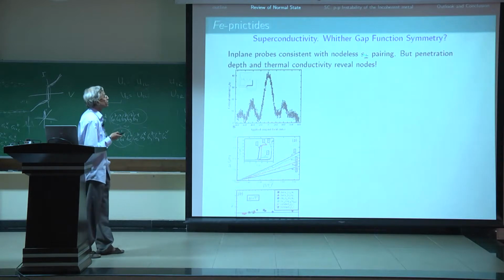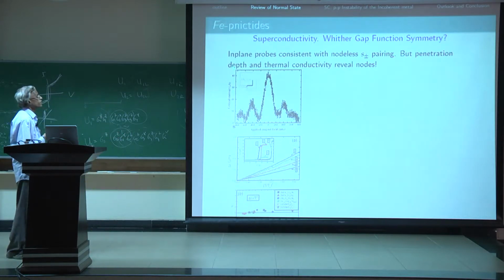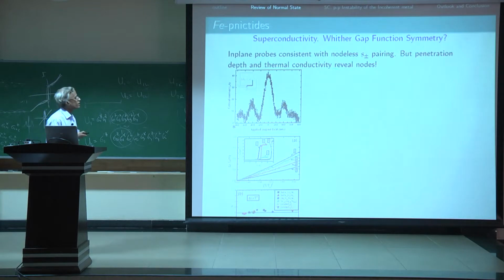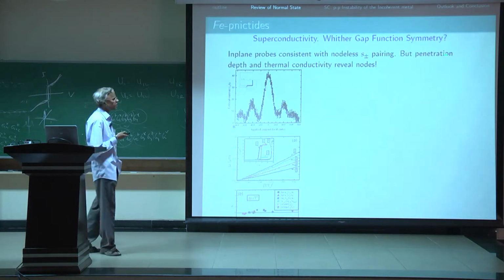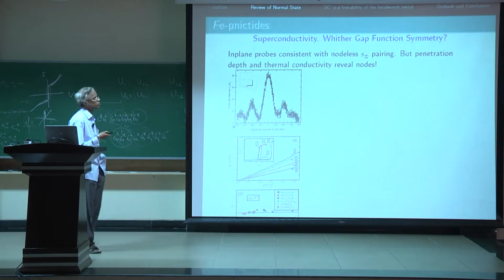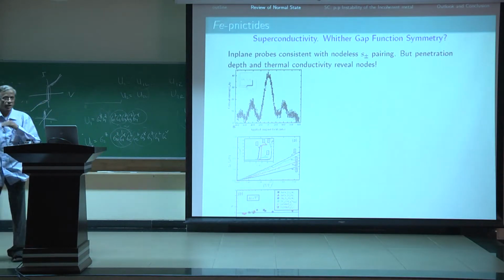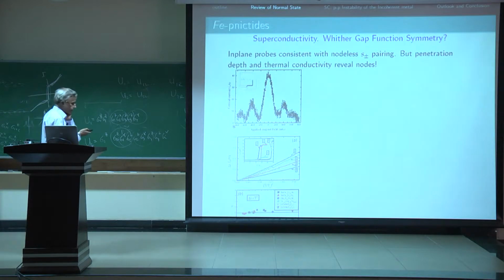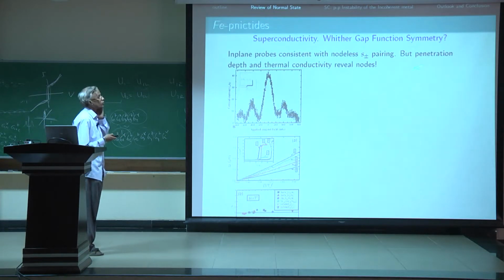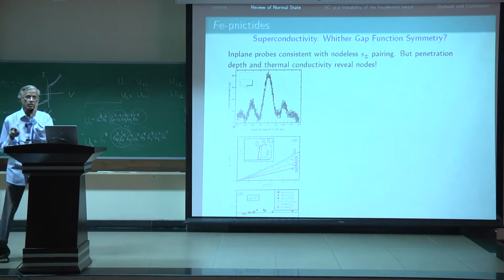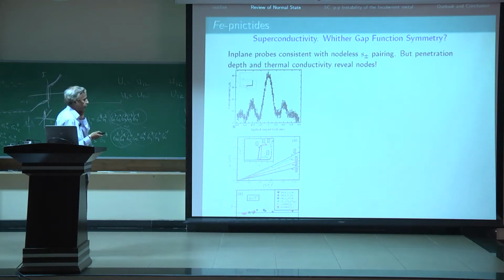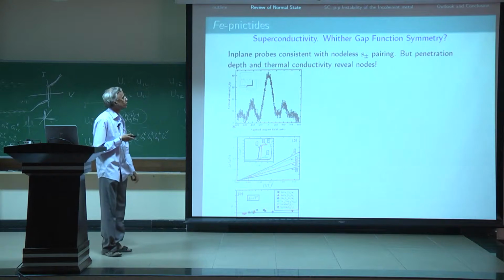What about superconductivity? Is it nodeless, or are there in-plane nodes or accidental out-of-plane nodes? This question becomes important. It's a multi-band system, and the Fermi surface in different systems shows a variable degree of warping along Kz, similar to what one knows from the well-known strontium ruthenate case. And in that context, there was evidence from heat conductivity measurements and so on that there were accidental out-of-plane nodes.